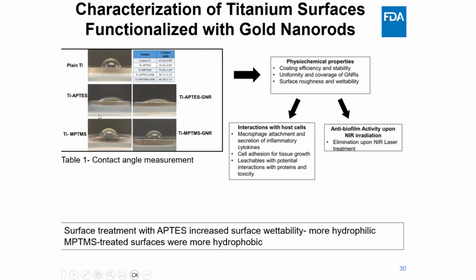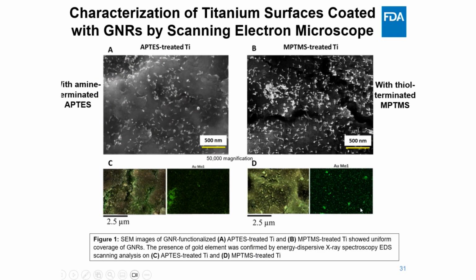APTES treated surfaces showed lower contact angles, indicating they are more hydrophilic and more wettable. In contrast, MPTMS treated surfaces were more hydrophobic with higher contact angles, showing less wettability. However, as we will see in the next slides, surface wettability alone does not determine the nanorod attachment. The strength of the chemical interaction is a more important and critical factor.